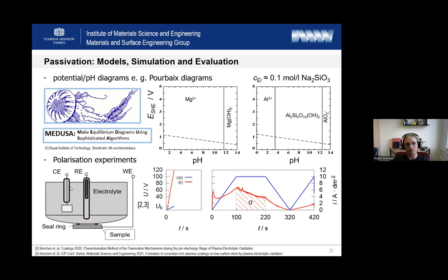We are working in 3 electrode arrangement. So our component, our sample is the working electrode. We have a counter electrode of platinum, and in the middle our reference electrode. And now we apply a special potential cycle.